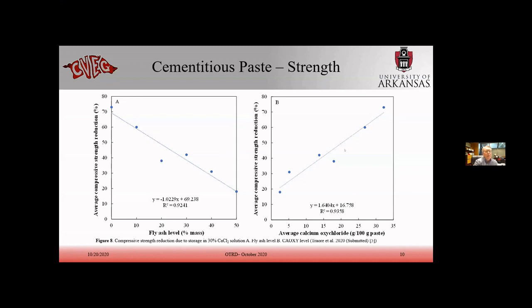Likewise on the other graph, this is what we get from the LTDSC, the average calcium oxychloride in grams per 100 grams of paste. On the y-axis you have the average compressive strength reduction. Same thing, it follows the reverse trend. There's 50% fly ash, 40, 30, 20, and then up to 10 and 0. So we have less calcium oxychloride at 50%, and as we decrease our fly ash content, we have more calcium oxychloride.